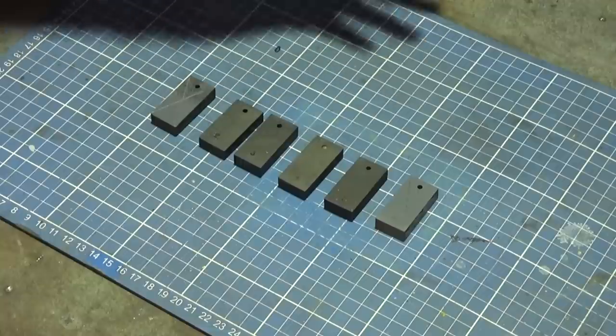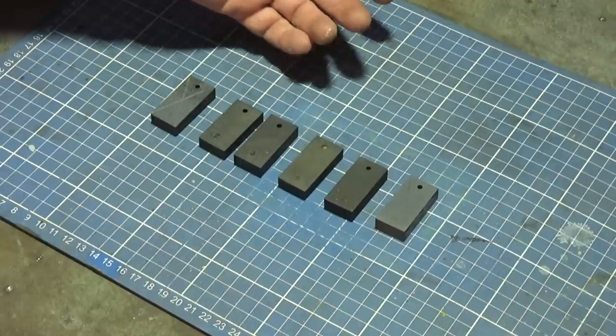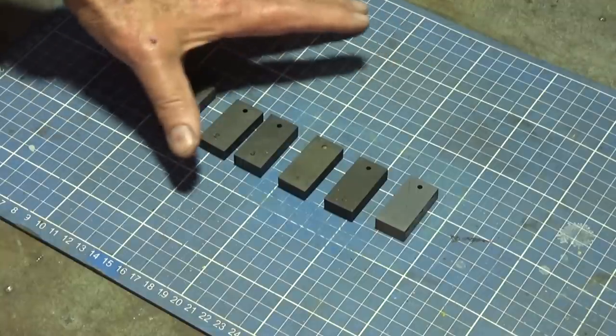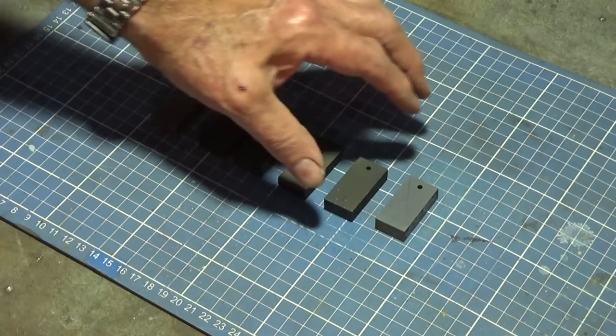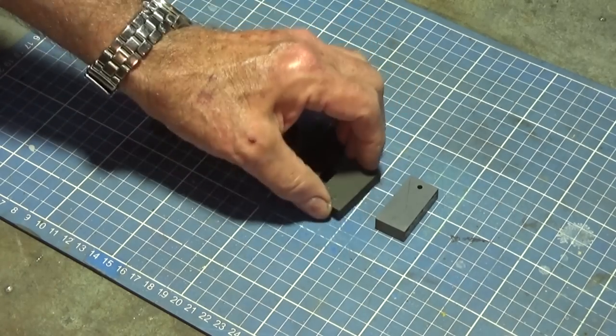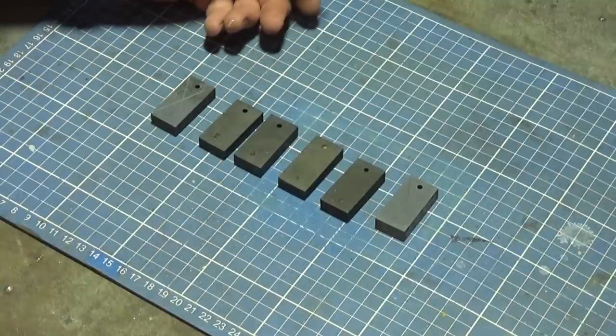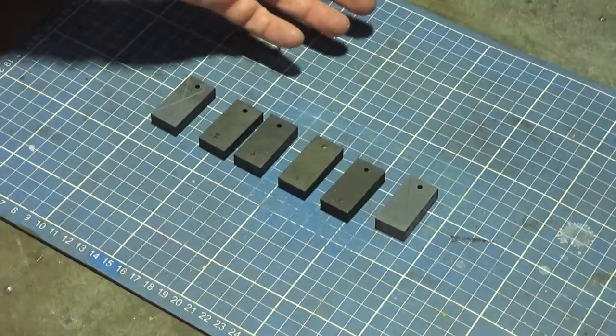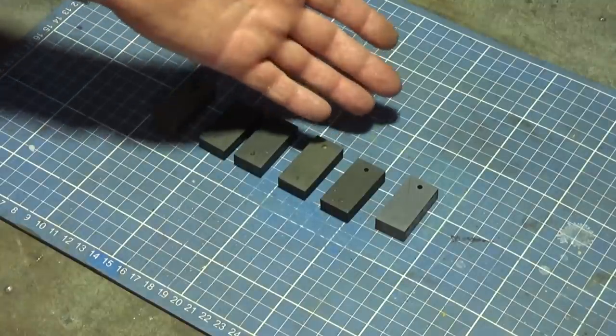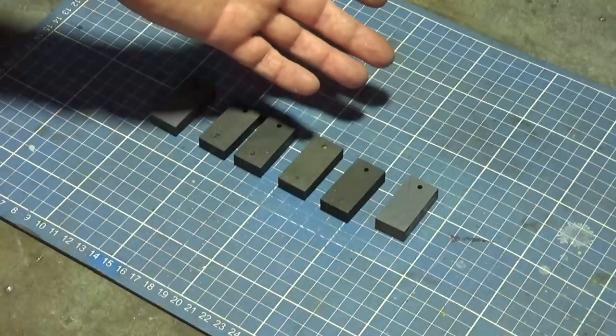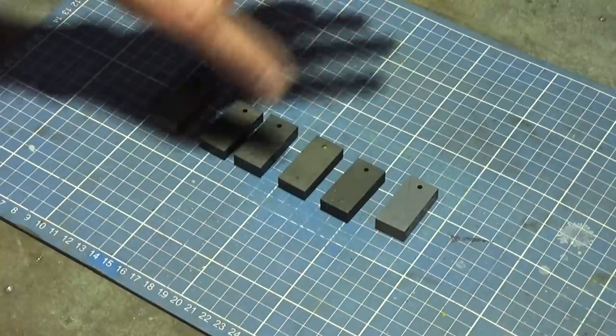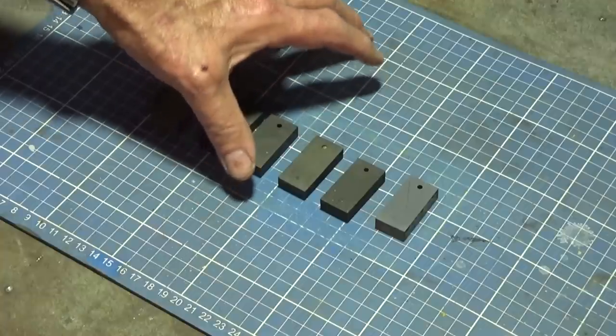In terms of 2, 3 and 4, it didn't seem to matter what sort of after treatment we used, they all held up equally well. 5, with the abrasion test, I don't know what I was expecting there. It's clearly damaged, and I don't think any sort of coating is going to protect it from the sort of abuse that we subjected that to.